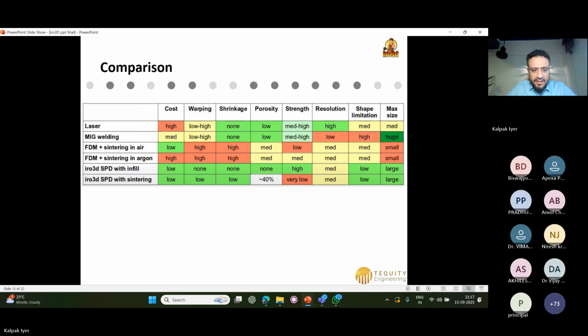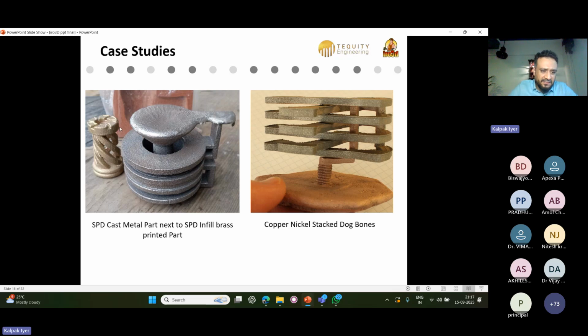Some more case studies: you can see we made a rook, which is made of brass. Then we made these tensile test specimens. These are monel or copper nickel tensile test specimens. This is actually a casting, which is also done through the mold that was shown in the first photo. So this is a stainless steel casting. You can see fairly good surface finish of this casting.